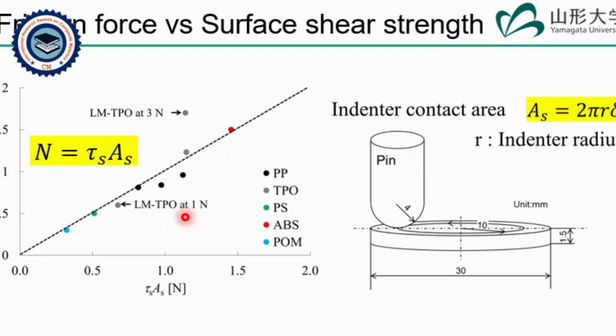The left figure shows a graphical comparison of the calculated and measured friction force. For most of the materials, the values calculated using this model were found to explain the friction force obtained from the pin-on-disk test. However, only LMTPO